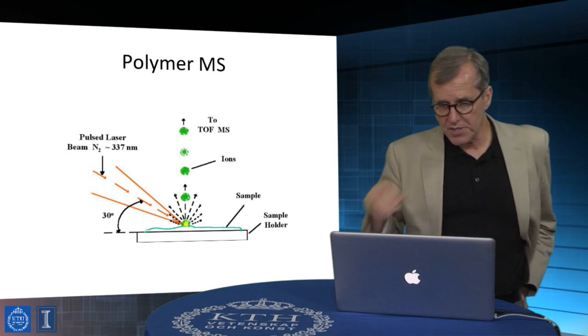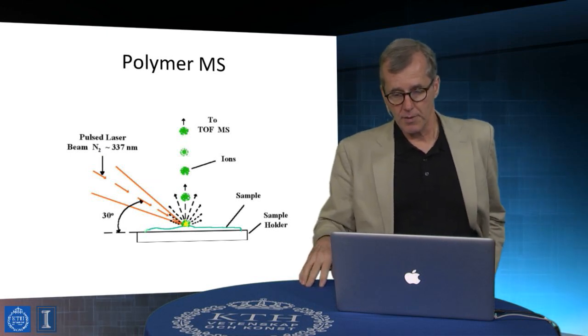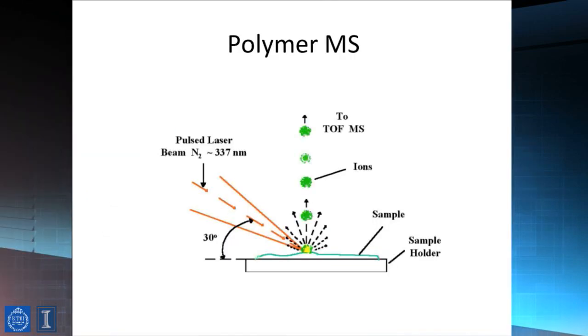And this is a physical description of the MALDI experiment. And as I said, there are other approaches, but this one's exemplary. So what we do is we have a sample substrate. The material of interest is placed on this substrate, and a matrix material is applied to it. These are compounds which are subject to photodegradation by, in this particular case, a pulsed nitrogen laser, irradiating it at 337 nanometers.